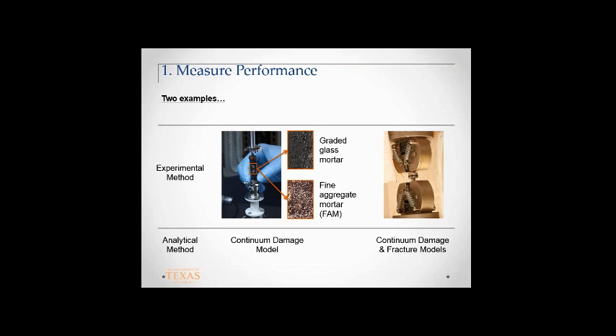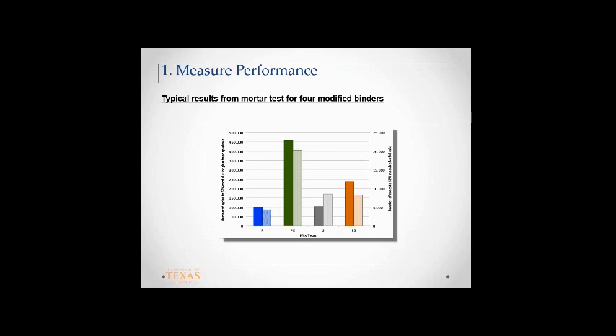We're not testing a large blob of asphalt primarily because a large blob of asphalt does not exist in an asphalt mixture. What exists is binder that is confined, experiences very high confining stresses because of the rigid aggregate particles surrounding it. So you take that and you recreate that in a more controlled fashion by either putting it in the form of a composite or by putting it in this kind of geometry here. So these are just some of the techniques that we're using to address the first question, and we're also developing them as we go along.